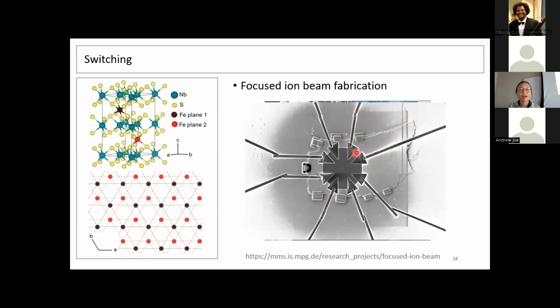These triangles are where I've cut away the crystal using the focused ion beam. And these lines are more cuts so that these conductive paths are separated from each other, and so that we have these really nice, sharp, perpendicular, well-defined paths for the current to go through. And this is a smiley face because I thought it looked like a little bug.